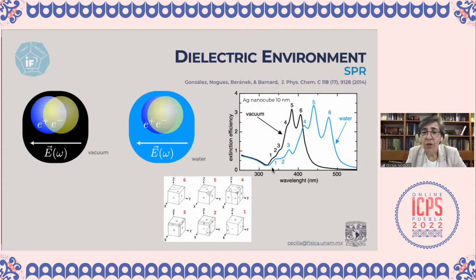And now when you have, for example, the silver nanocube in vacuum as compared with water, you still have the same number of resonances, because that depends on the shape of the nanoparticle. But now the forces that you need to have this resonance and this competition between the Coulomb forces, which are almost the same, but less strong because of the presence of the dielectric environment. Now you will have that these peaks are moved to smaller frequencies or larger wavelengths.